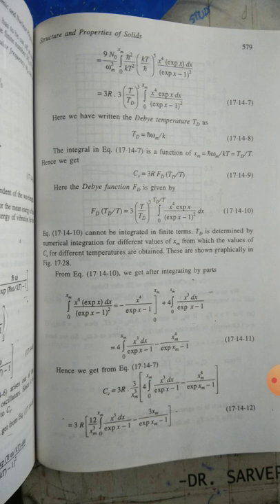Hence we get Cv is equal to 3R FD (TD by T). Here the Debye function FD is given by FD (TD by T) is equal to 3 into (T by TD) cube times the integration from 0 to TD by T of x to the power 4 e^x dx by (e^x minus 1) square, which cannot be integrated in finite terms.